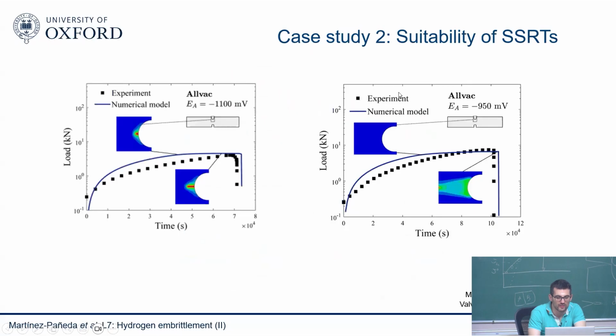And we actually try to change the environment and go from a more aggressive environment to a less aggressive environment. From the permeation test, we knew what the hydrogen concentration was, so we put that into the model. And as you can see, the model seems to have attained a very good agreement. So that was quite nice to see.